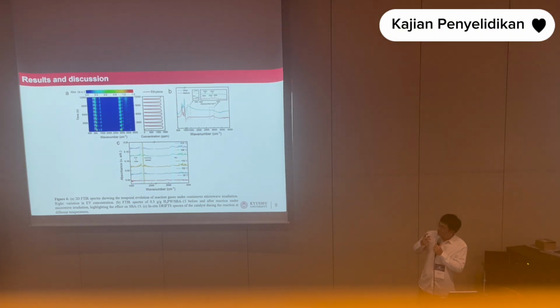And here we tested with cycling to prove the sustainability. After the cycling test, the ethylene yield still stays at a high level. And we compared the catalyst before and after. We can find some CH2 bond and something in it. The HPW still exists.